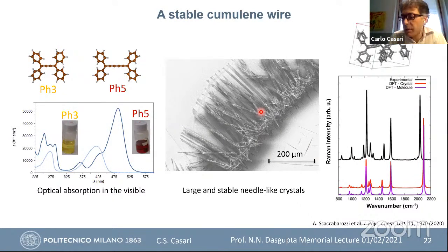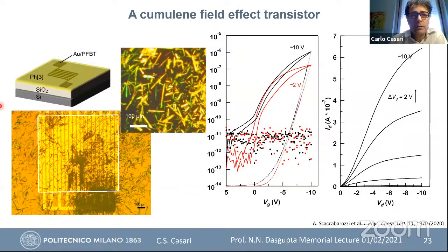And for this material, we tested electronic applications. So in collaboration with Mario Caironi at the Italian Institute of Technology, we were able to produce a field effect transistor in which the active material is the cumulene wire that I showed you before, deposited on interdigitated electrodes. You can see here the covering is not very good, but it was the first proof of concept. You see here by optical microscopy the needle-like crystals I showed you in the electron microscopy image before. And as the first proof of concept, the transistor works quite well, and we are still improving the performances by engineering the deposition process.